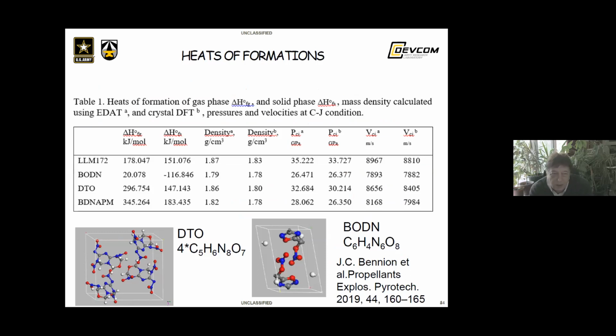Here we present heats of formation calculated with EDAT heat together with mass density for LLM-172, BDNAPM, and two other explosives, BODN and DTO. BODN is a melt cast explosive material that is potentially both a more powerful and environmentally friendly alternative to TNT. DTO is a relatively new energetic material with multiple potential military applications. It is important to mention that DTO has four molecules per unit cell and BODN only one molecule per unit cell. The fewer the molecules in a unit cell, the closer the values of mass density calculated using EDAT and crystal DFT. They're almost identical for BODN.